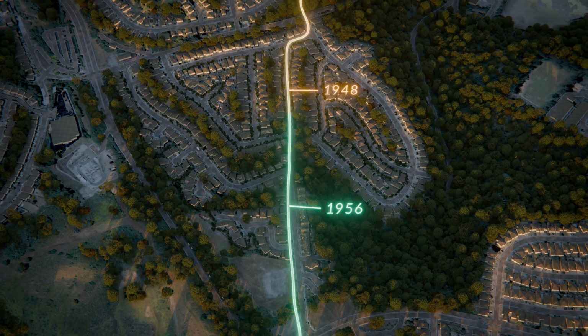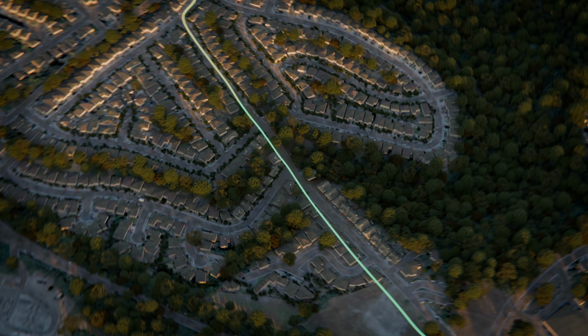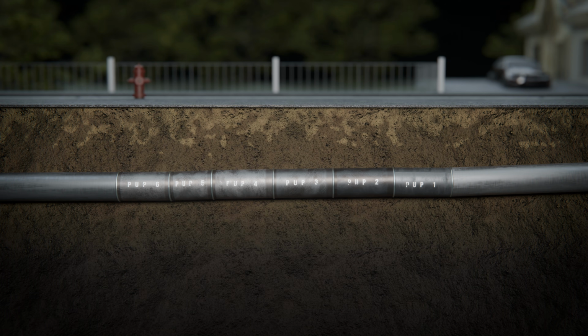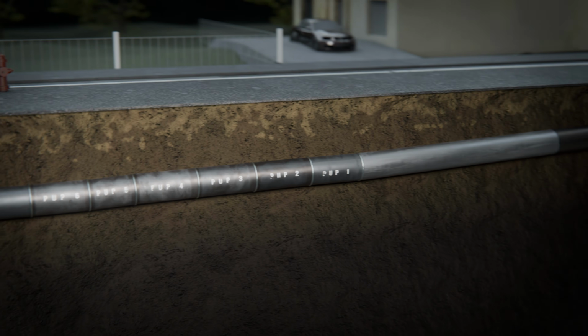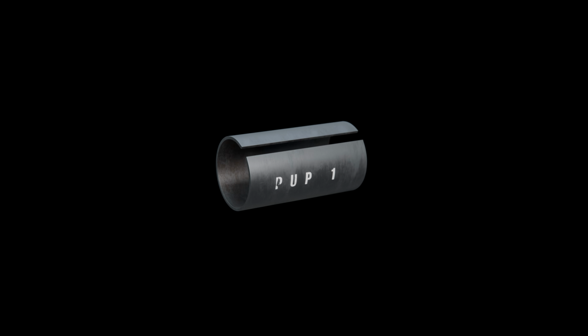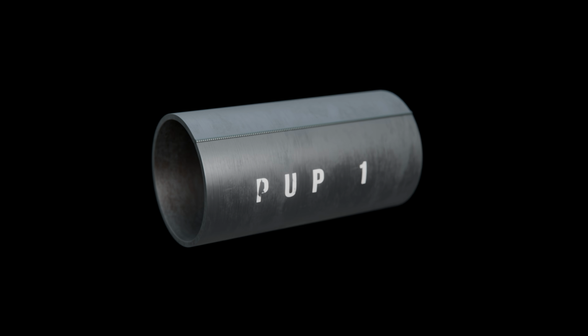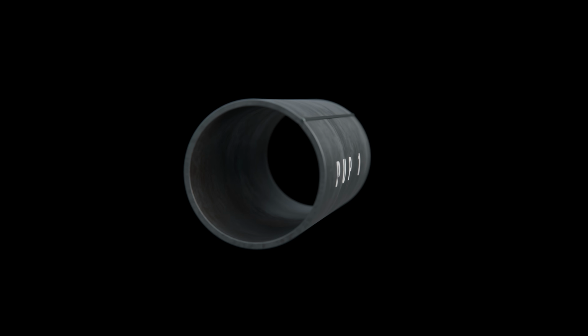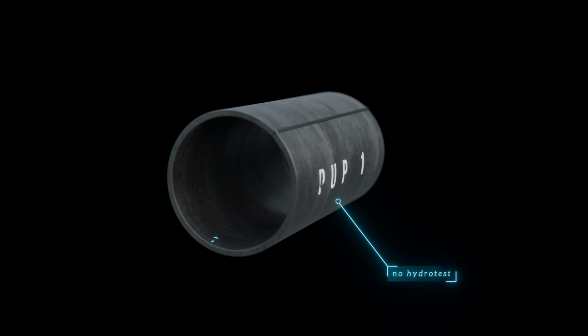The failure originated at a longitudinal seam weld in one of 6 short pipe sections, known in the industry as PUPs, that were installed as part of the 1956 rerouting work. Unlike the standard pipe used in the rest of the line, these PUPs were formed using a non-standard welding process that introduced significant defects on the internal surface of the seam weld, which acted like sharp cracks. These defects were so severe that the pipeline would likely have fractured immediately had this section of the line been hydrotested. But the hydrotest was never performed, and the line was never inspected either.